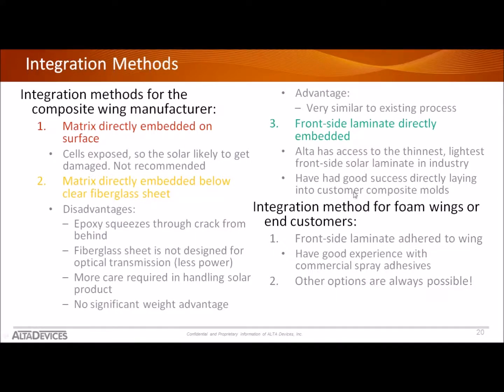One thing I didn't highlight from above is that we actually are working with solar front sheet manufacturers to develop and push the envelope of what the industry can do. So we believe this to be the thinnest, lightest front side laminate of solar grade material. It's been custom designed for us by a domestic manufacturer, and right now we have quite a bit of the material that we can use, and that is the material we would recommend for either integrating in the wing or adhering to the top surface.